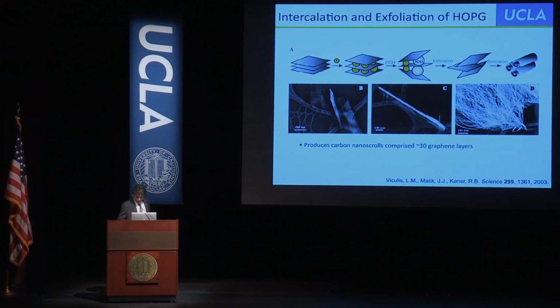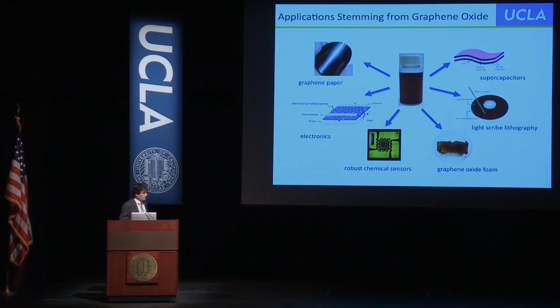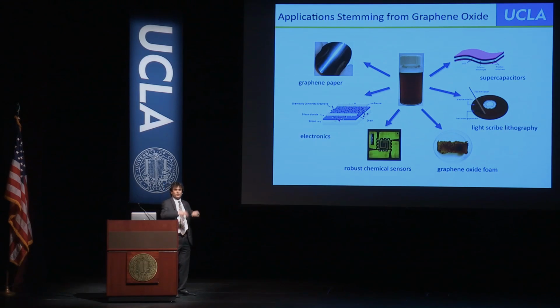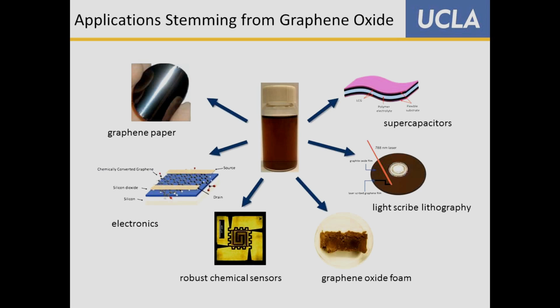someday be recognized. Okay. After Viculis and Mack did their work, we realized that the only problem with our method is it not only makes one layer, as people have subsequently shown, but it can make 2, 30, all different numbers of layers. So we switched our research a little, and we started looking at graphite oxide, which is if you oxidize graphite in water, you can divide it into individual layers that are oxidized, and then you have to get them back to graphene.